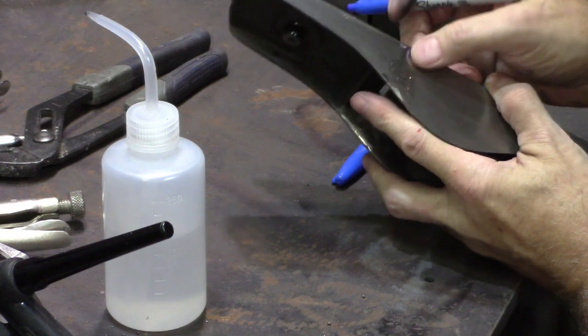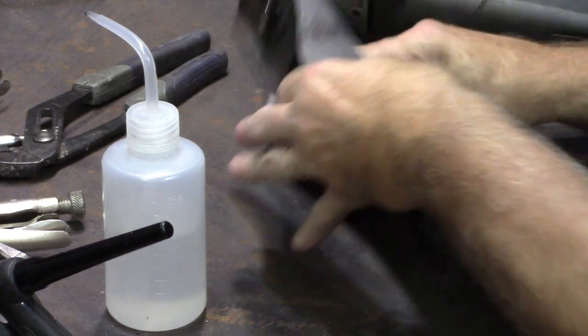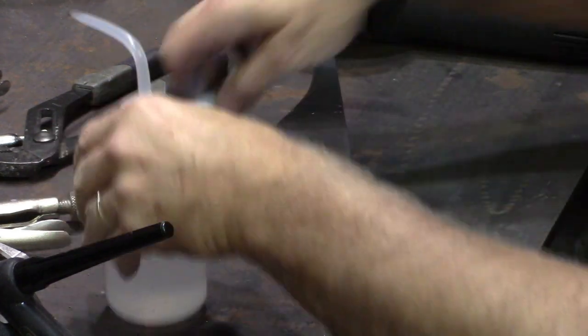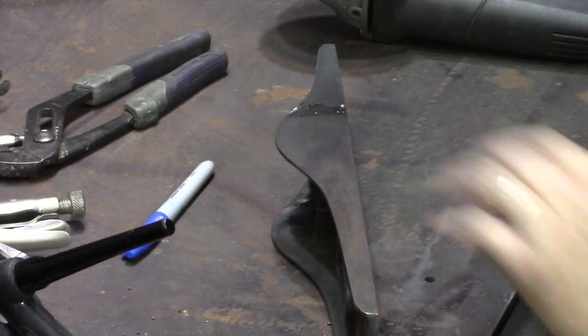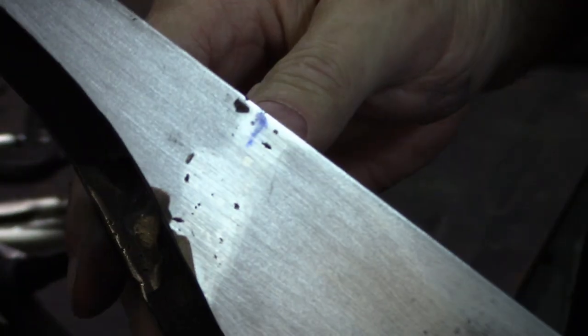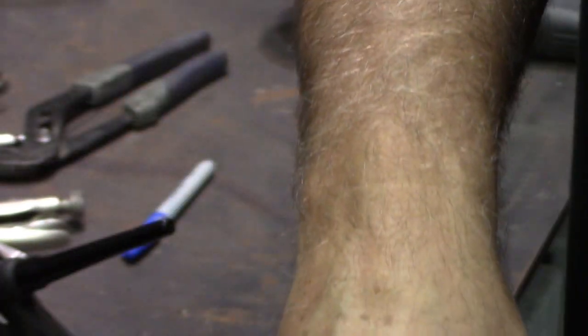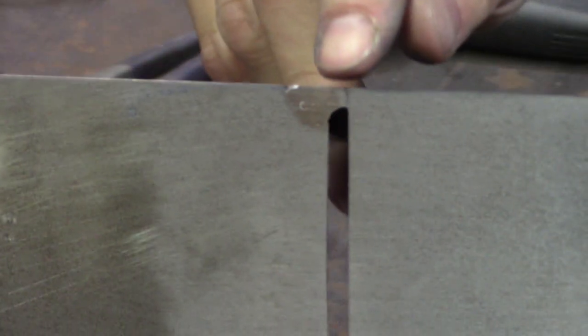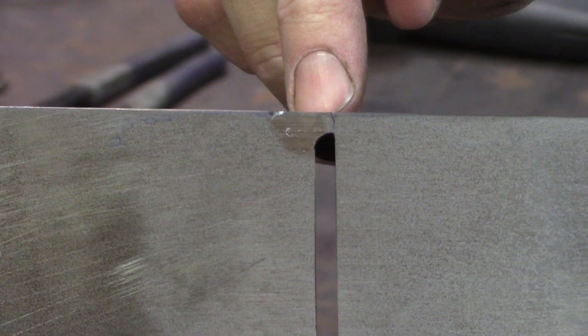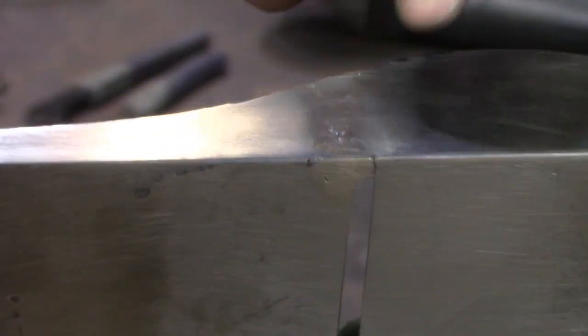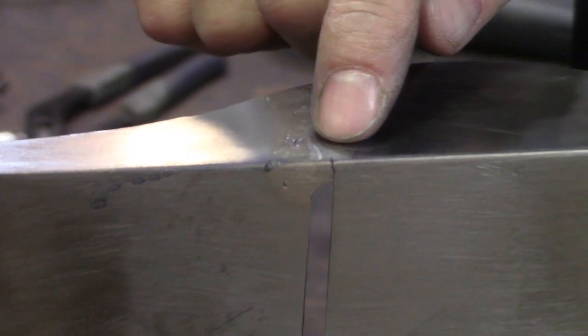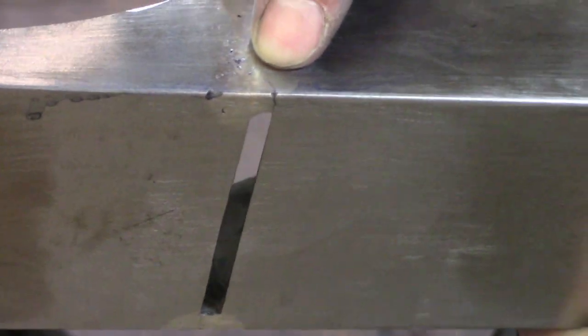So any place I think there might be a problem, you can see I'm marking it with a Sharpie. And yep, I did find a crack. I'm not going to go back and show you how I fixed the crack, because basically all I did was I ground it out, and I went back and heated it back up. There's the crack right there. I'll give you a better picture in just a second. I'll put a little more acetone on it and make it easier for you to see it. Can you see it right there at the tip of my finger? Little tiny crack. It's coming up the side of the web just a little bit. So what I'll do is I'll grind that out, and then I'll re-weld it once I reheat the piece.